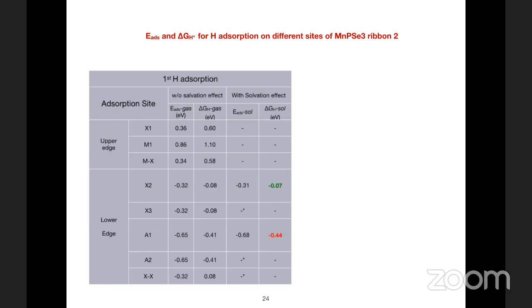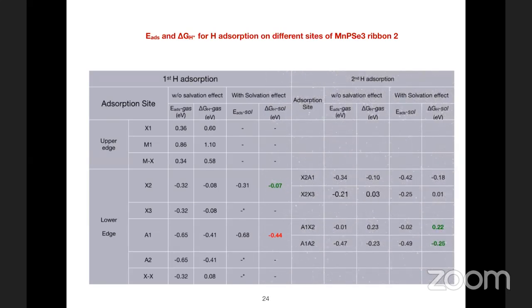But when you have a larger concentration of H+, some of them would get adsorbed at A1, and then they would be difficult to remove. So what happens in that case? Because they are not that far apart anymore. In order to answer that question, we calculate delta GH for the second hydrogen when one hydrogen is already adsorbed at the A1 site.